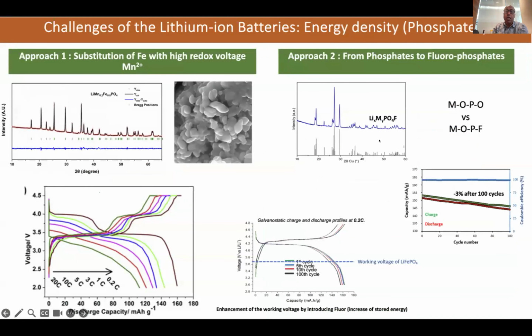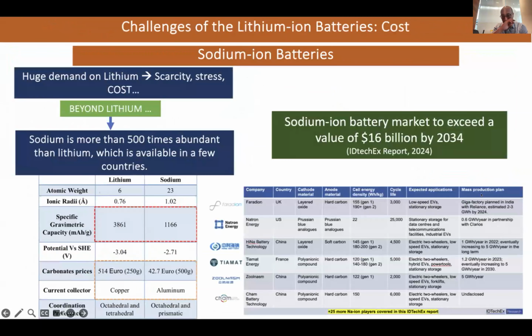The second approach is how we introduce fluorine, because OCP is producing phosphate, but it's producing also fluorine. And we developed this new material, and you see here, I compare the voltage of LFP with the voltage of our material, and you see we improve from 3.7 to 4.3 volts. And we see here that we have good stability.